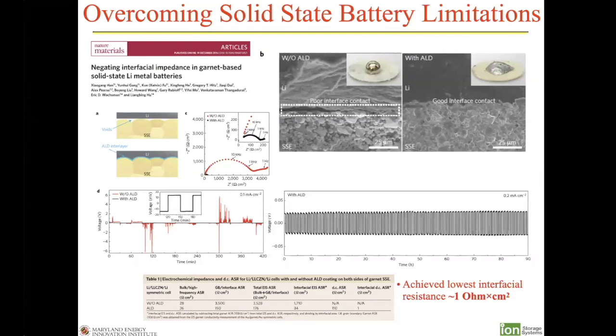So we've blown that up so you can see the symmetric square wave cycling we can obtain with that ALD process. The data to the right is just showing you, again at a higher current density, how uniform that is and how it can go on for hours and hours without any problem, a very, very stable cycling. And if you subtract the electrolyte impedance from the total symmetric cell, you get an interfacial impedance, which is on the order of about 1 ohm-cm².